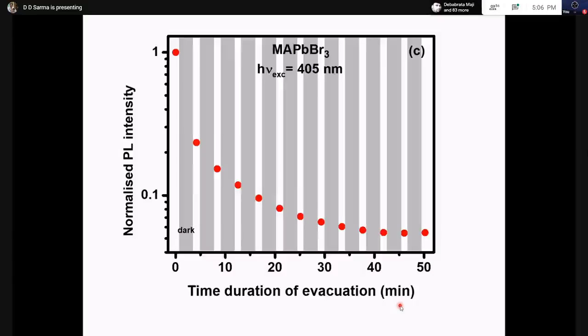And this can be done by doing what is known as a two-photon absorption technique. So basically, you come in with a photon whose energy is less than the band gap energy. So one photon doesn't get absorbed. But you have a sufficient number of photons such that at times, two of the photons combined simultaneously make an electron hole pair. Since this has an absorption probability that is very low, an absorption coefficient that is low, the entire bulk of the material is uniformly illuminated, and the signal comes from throughout the bulk of the material. And when it combines and photoluminescence happens deep inside, it comes out and doesn't sense the surface defects. And you can do the experiment safely.